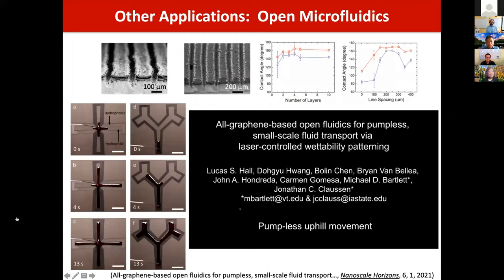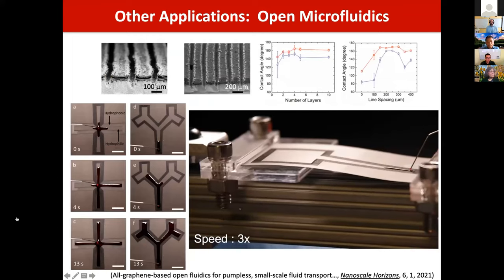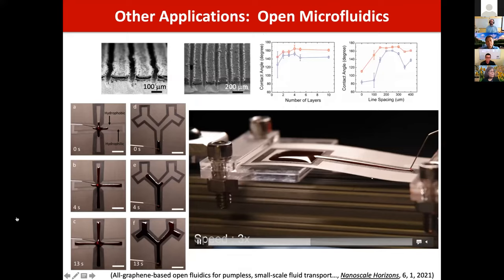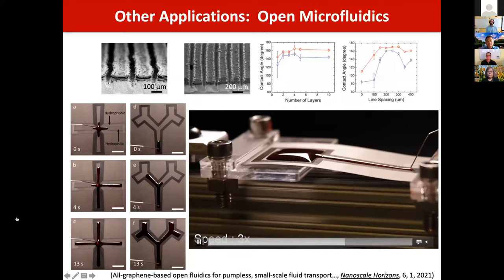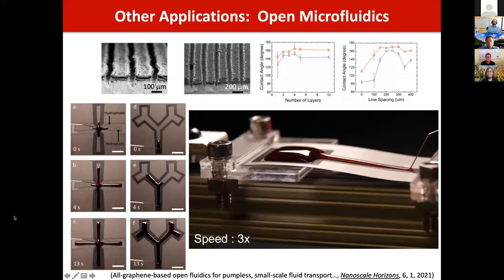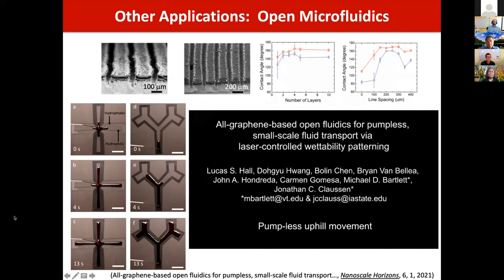So other applications that we could do with this: open microfluidics, because we can tune the surface wettability of the graphene from hydrophobic to hydrophilic. We can actually move fluid across the surface because there are hydrophobic sidewalls and a hydrophilic track. By Laplace pressure, water will flow through these tracks, through these wedge patterns. We can split samples to do multiplex sensing, and it's strong enough to even move uphill.